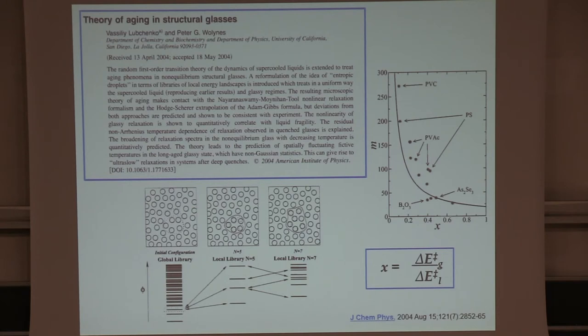The glass is, at least initially, an arrested liquid. You've gotten to a place where you've fallen out of equilibrium. You can't grow these clusters any bigger, but you can still see a few of them move around a bit. And that gives a very slow relaxation in the system. That slow relaxation near the transition is itself still very Arrhenius-like.